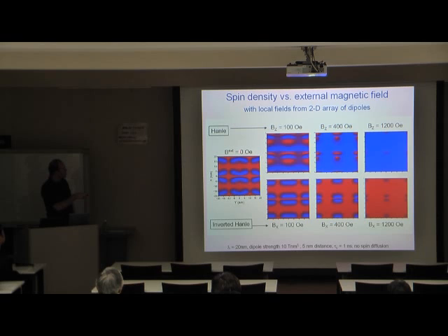So at zero external magnetic field, we see that as a function of the lateral position, there's inhomogeneity in the spin accumulation. You have regions in blue where the spin accumulation is suppressed to almost zero, and regions in red where the spin accumulation has hardly any effect. What you can now also do is do these calculations as a function of external magnetic field in the z direction, which suppresses the spin accumulation everywhere, or with an in-plane magnetic field, which shows you a recovery of the spin signal everywhere due to what I refer to as the inverted Hanle effect.